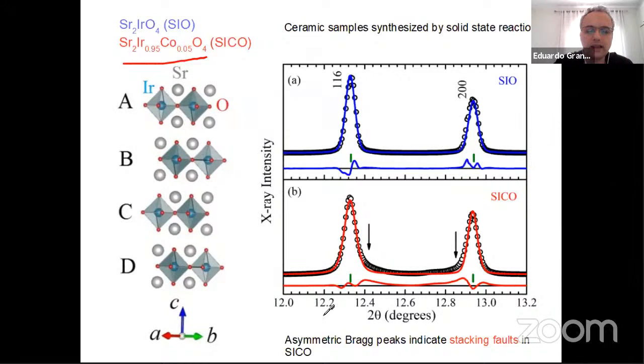This is an X-ray diffraction profile around a pair of Bragg peaks, 116 and 200. SiO means strontium-2, iridium oxygen 4, pristine, without doping. SiCO means the cobalt doping. That's what we are really interested to check. We note that the Bragg peaks are not very much broadened by this cobalt substitution. This is a synchrotron X-ray diffraction experiment, and the difference between the angles of these two reflections is just 0.5 degrees in theta. So the width is not large, neither for the pure sample, nor for the doped sample. That gives us hope that the doping did not disturb too much the crystal structure.